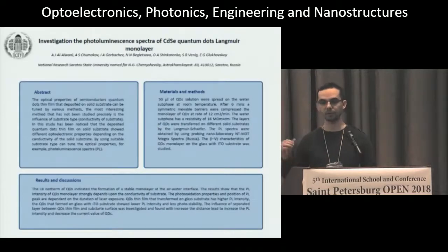Also, we studied the influence of the distance between the layer of quantum dots and the substrate by inserting an insulator liquid crystal. With increasing the distance between quantum dots and substrate, this will enhance the photoluminescence spectra of the quantum dots. This is our topic, and thank you very much.